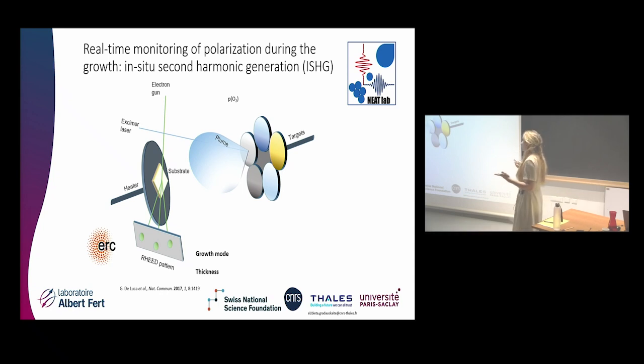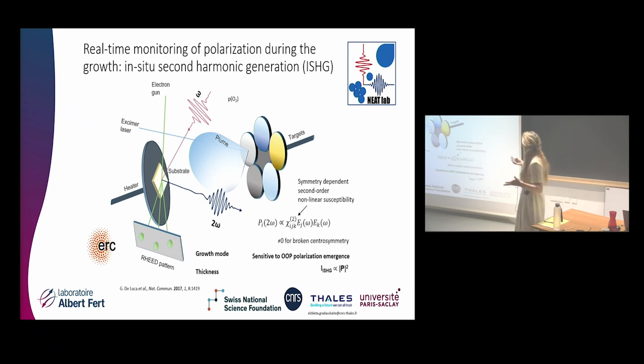But what's very important is that in my lab we had a femtosecond laser coupled in our PLD chamber. So we had essentially a means to probe symmetry breaking. We were looking for frequency doubling of light. So this is SHG. And it's known that this is only allowed when a material has a broken center of symmetry. And with the way we select the components we're probing, we know that we will measure a signal that is sensitive to out-of-plane polarization emergence. So having a setup like this allows us to really track polarization at the interface and what is happening in real time.